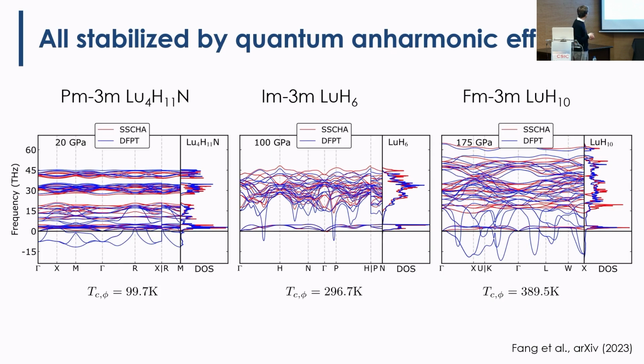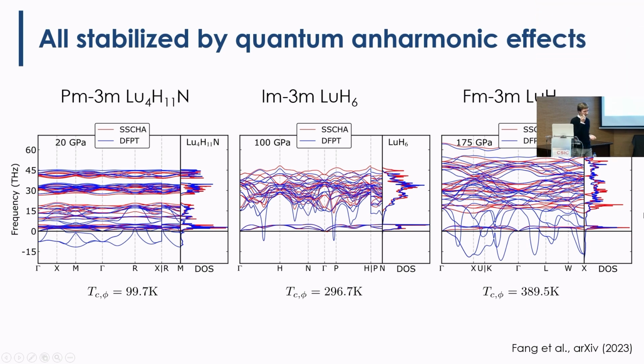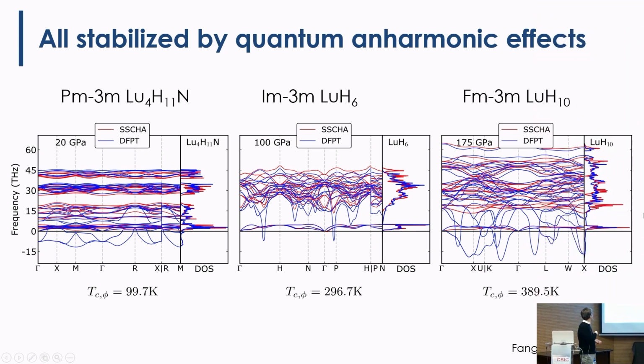So it's interesting that all of these structures are stabilized by quantum anharmonic effects, okay? I'm going to talk about that later. And here at 20 GPa, okay, these are dynamically unstable below these very high pressures. So, I mean, these will never be able to be synthesized at low pressures. But this one, I don't know. So here we believe that above 20 GPa, this is dynamically stable.